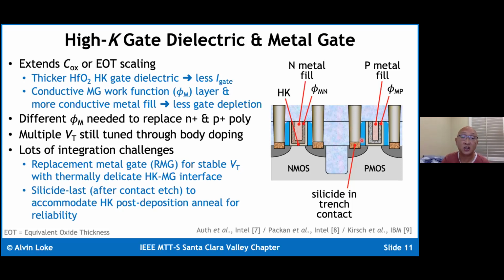Okay, and to further complicate things, one other key process integration step that was required to make HighK metal gate technology happen is to move the silicide module. Historically, the silicide module happens before you deposit the contact dielectric, but with the replacement metal gate integration happening after the contact dielectric's deposited, typically there's a post-deposition anneal that you need for making your HighK dielectric more reliable for TDDB, time-dependent dielectric breakdown concerns. That high temperature causes the silicide to actually disintegrate if you introduce it too early. So to deal with this, the silicide is deposited at the bottom of the trench contact once the diffusion contacts are formed.